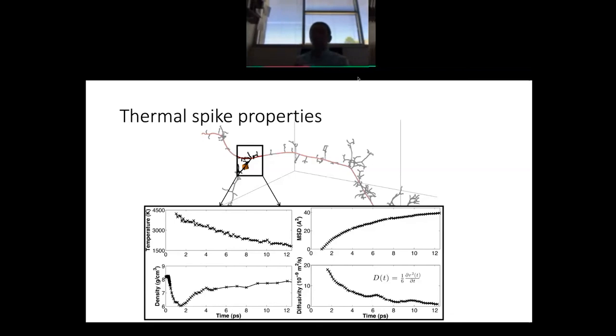our qualitative conclusions, which is that beyond a layer thickness of about 2 nanometers, the pinch-off events do not occur. Now, our interpretation of that is that in the cases where pinch-off does not occur, the reason is not related to the parameters of the phase field model. It's really not related even to the solid phase demixing process. It's more related to the fact that the interdiffusion zones in the thermal spike never have a chance to overlap, right?